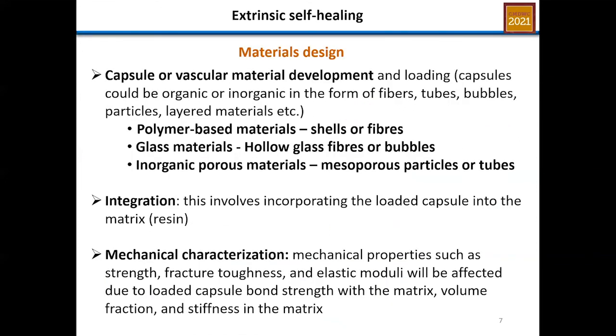But when we talk about the extrinsic healing, we are looking at how to design the material in such a way that the healing agents are encapsulated. Now, various kinds of encapsulating materials have been explored by various research groups, and this could be in the form of fibers, tubes, bubbles, particles, layered materials, either from polymer-based materials or from glass materials, or inorganic porous materials. And the main aim is to ensure that they are incorporated into the matrix after they have been loaded with the inhibitors, which now act as the healing agents.